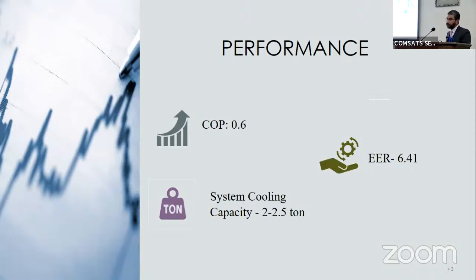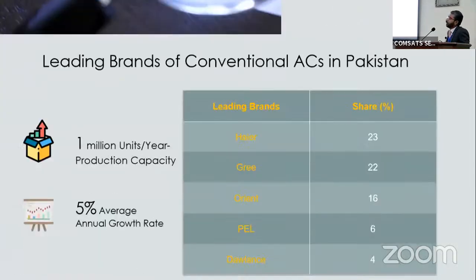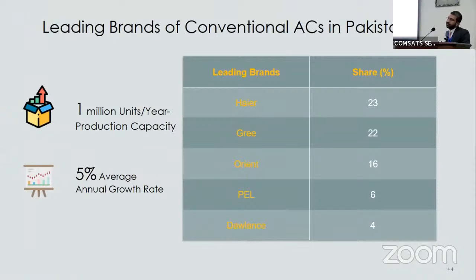It's not bad, although it's quite low as compared to a conventional air conditioning system whose COP is more than 1.5, around 2. But just have a look at the EER, the energy efficiency ratio. It's around 6. It's quite good. The system which we have developed has a cooling capacity of 2.5 tons. It's quite a good solution for domestic application, because normally in domestic application we have 2 rooms, and a system of around 2.5 tons of cooling capacity will be enough. Now, the important thing is that we have to launch it as a product.